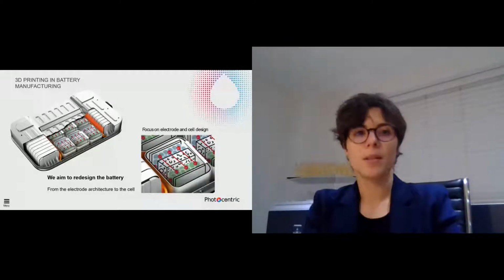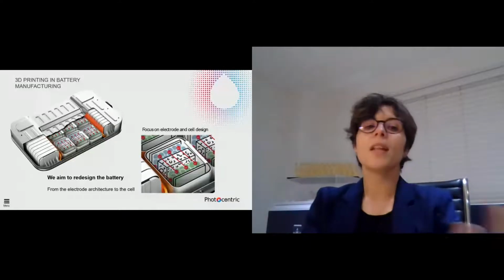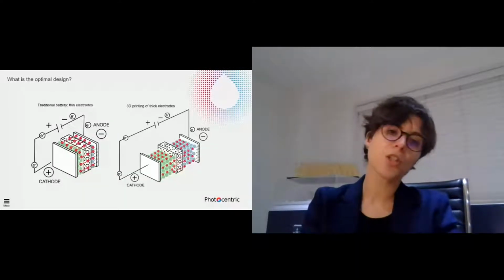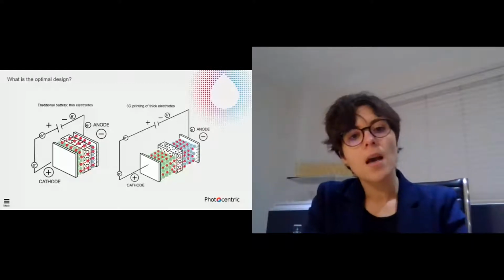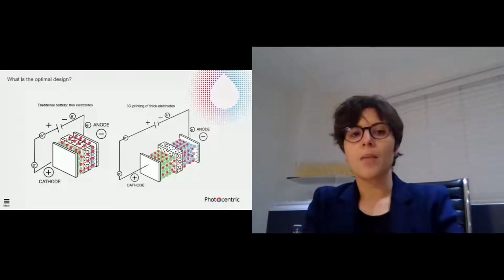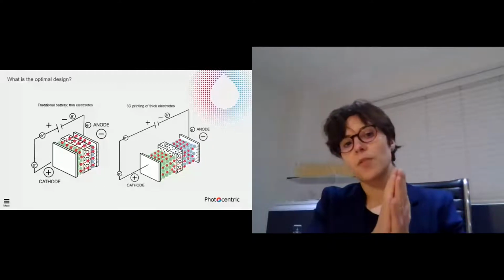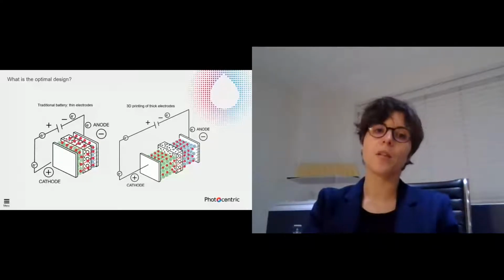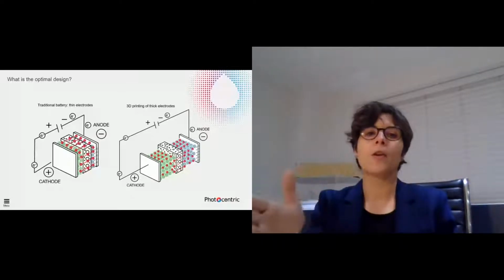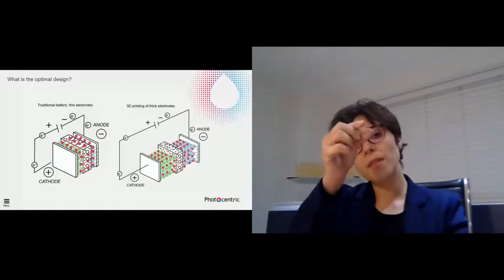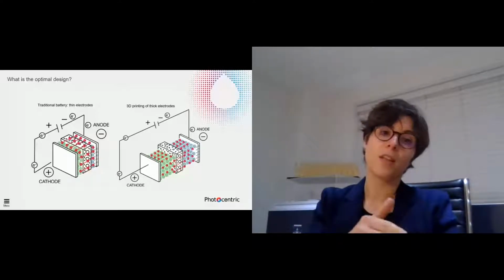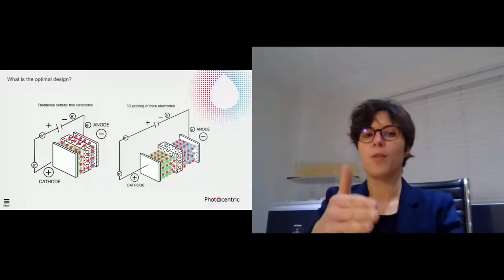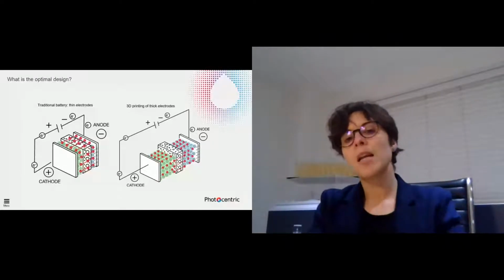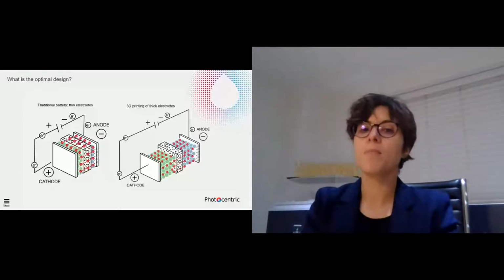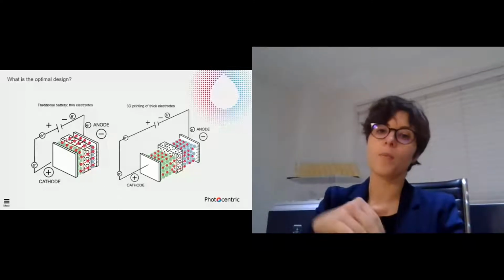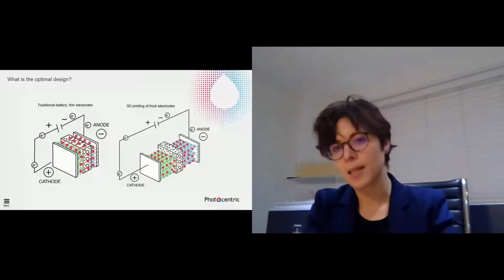And what is the optimal design? On the left side, you see a traditional battery. A traditional battery, lithium-ion battery in this case, has thin electrodes. And basically, the capacity of your electrode and therefore the performance of your battery depends on how many lithium ions can flow from anode to cathode and back. So whenever you have thin electrodes, you have a limited number of lithium ions which will flow from cathode to anode and back. Whenever you have thick electrodes, you have obviously more lithium ions that can flow from cathode to anode and therefore an increased capacity.